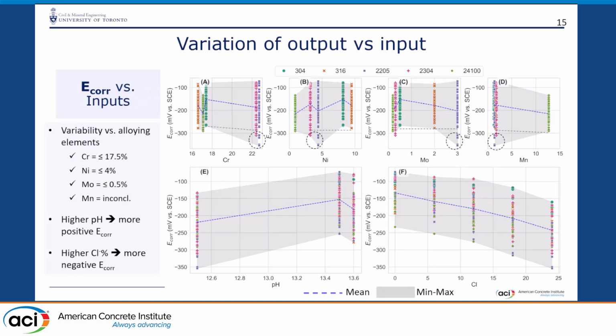Having a look at the influence of chromium, nickel, molybdenum, manganese, it is much more straightforward to look at the pH and the chloride because you can see an increasing and decreasing trend, which is something you're familiar with. As pH increases, your corrosion potential becomes more positive, which is good. And as chloride increases, your corrosion potential becomes more negative. So that's something very familiar. However, the alloying composition is neither here nor there. It is somewhat clear for corrosion when you look at chromium. You have a decrease in trend after 17% chromium content. Before that, you have more positive on average, and after that, more negative, which suggests there's not much benefit in the high pH environment where we're using stainless steel from increasing the chromium content beyond 17%.